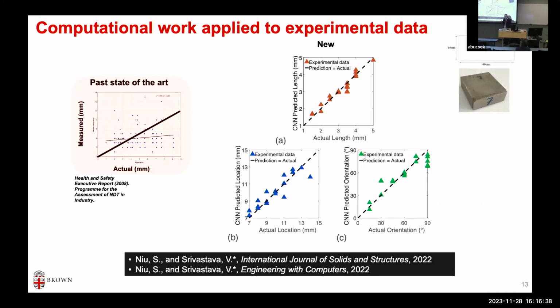So the CNN was trained on computational finite element simulation. We built an experimental setup, bought an ultrasound that's used, and we made these samples with cracks inside that look like this, with embedded 3D cracks that you cannot see, at different locations, angles and different sizes. And we took the ultrasound measurement and fed it to that CNN. This is the prediction for the actual experimental data, for a CNN that had never seen the experiment before. You see how accurate we are in predicting the length.